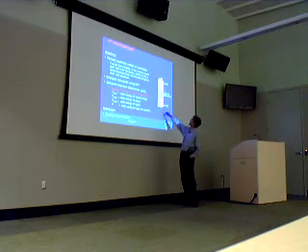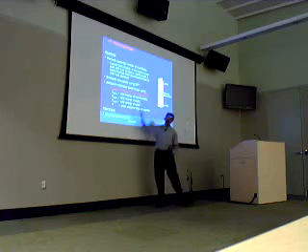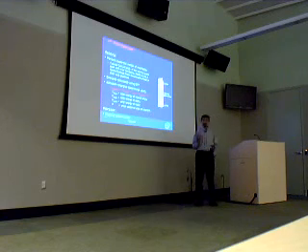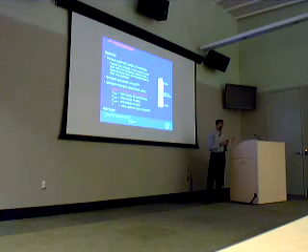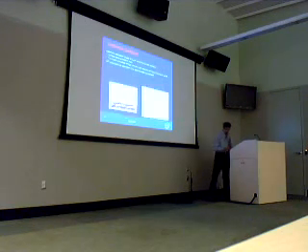And this is very straightforward for our calculations here. What we did was we put a stack, which is copper, and then we put in the material that we wanted to look at the adhesion. And we estimated the energy of adhesion of these different materials. Now, one subtle point here. The real copper is not single crystalline, but we looked at single crystalline materials because the polycrystalline is a very hard problem to solve with ab initio. But the single crystalline material predictions turned out to be pretty good.